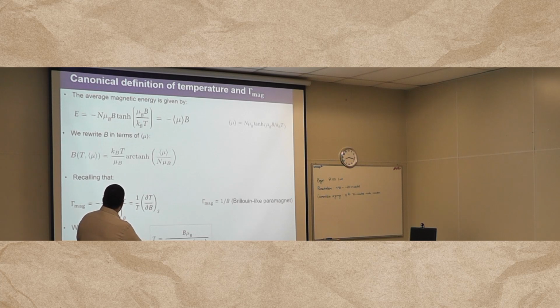We solved this for B as a function of T, because we know that gamma mag can be written in terms of the entropy derivatives, but it can also be written in terms of the temperature derivative at the respective field. So we took this derivative of B over T, which is exactly this to the power minus 1, and making use of the result for the paramagnet, we have seen that temperature can now be defined with respect to the average magnetic moment. If the average magnetic moment is positive, the majority of spins are aligned parallel to the field, which is associated with a positive temperature. If the average magnetic moment is negative, the magnetic moments are in an antiparallel configuration, so the temperature is negative. So we have unprecedentedly connected the magnetic Grüneisen parameter with the definition of temperature to show that the definition of temperature is encoded in the magnetic Grüneisen parameter and vice versa.